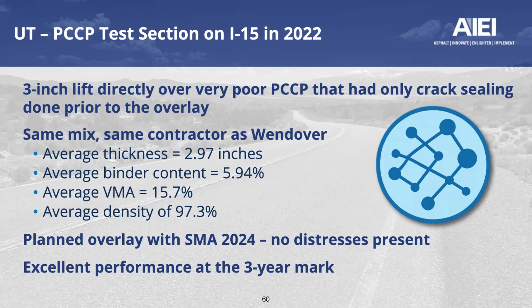So they chose to lay down 3 inches of material. They hit their target of compacted thickness very closely. The average binder content was, again, real close to that 6% value. Their average VMA, as we can see, was a little bit higher in this case. We were 15.3 at the mix design, and they were hitting in the field a 15.7 at this I-15 overlay.